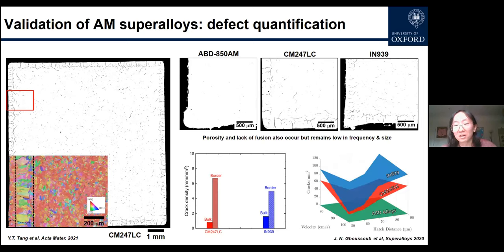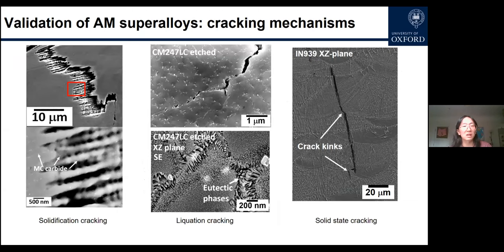You can also do your DOEs and try to find the best processing conditions for each of these alloys. And you realize the trend is not changed, even though the absolute numbers may change with the processing window. In order to really understand and feed back into our models, we have to understand exactly what happened in terms of those cracking. So we characterized some of those cracks in our SEMs, and we found there are three main types of cracking we have to consider. One is solidification cracking, the second type is liquation cracking, and the last one is solid state cracking. So we have also tweaked our models and added some other criteria to help us screen out for the next iteration of our alloy design effort.